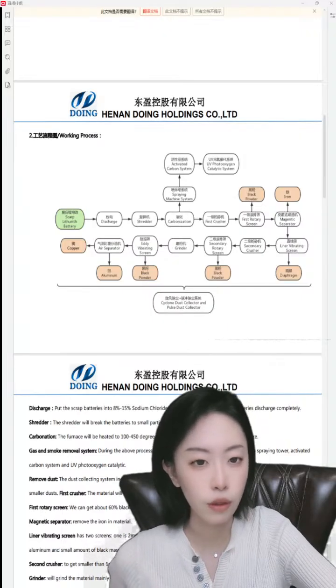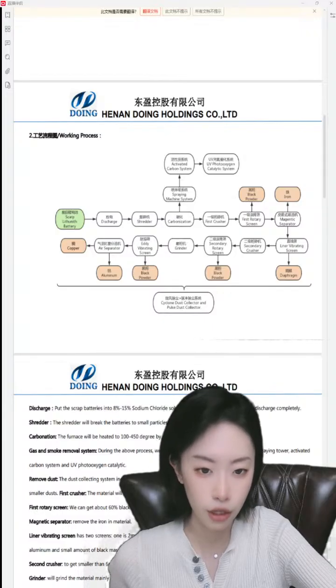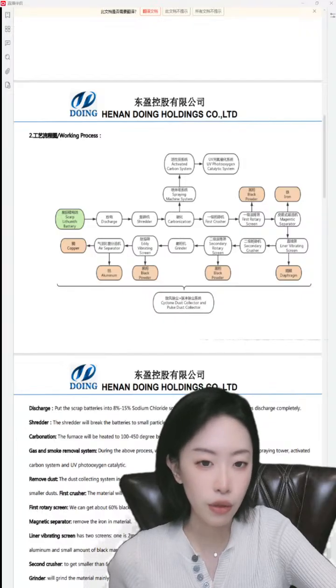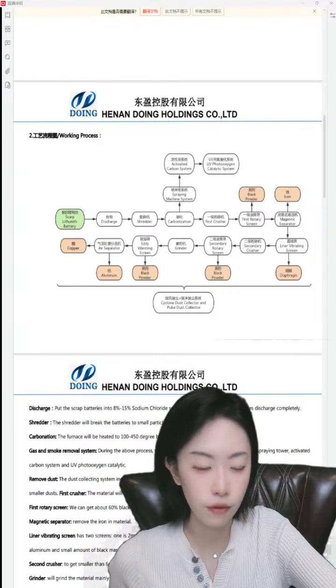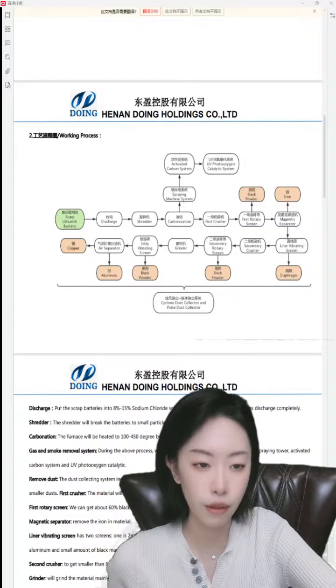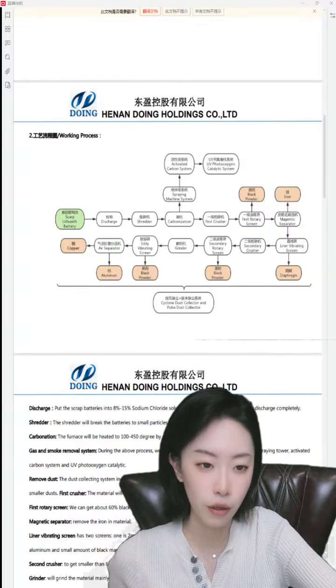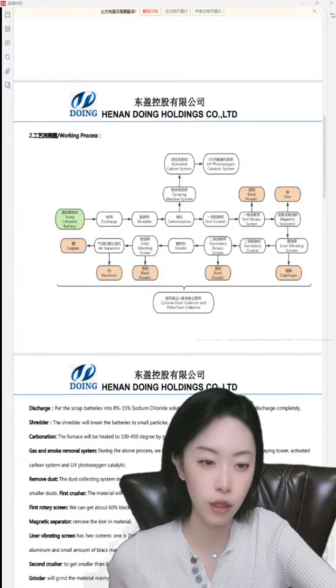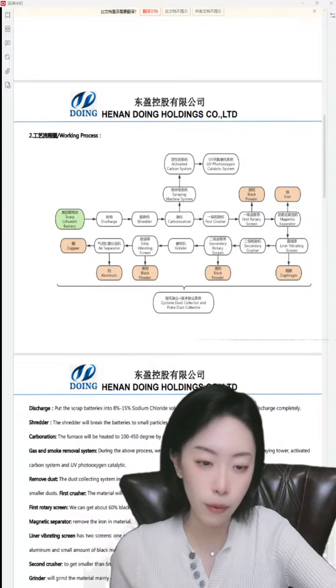Then the particles will go into the grinder, and the grinder will grind raw materials at a granular shape, grinding to finer particles. Then they will go into the rotary vibrating screen. The rotary vibrating sieve is equipped with a 50 mesh screen in the upper layer and a 120 mesh screen in the lower layer. The small amount of the black powder comes out from the lower layer of the rotary vibrating sieve, and the middle layer sieves out the copper aluminium mixture into the next level for the sorting machine. And the rotary vibrating screen is a high precision sieving machine with low noise, high efficiency, and fully closed structure, suitable for screening and filtering of granular, powder, or other materials. And in this step, the black powder here can be recovered about 99%.